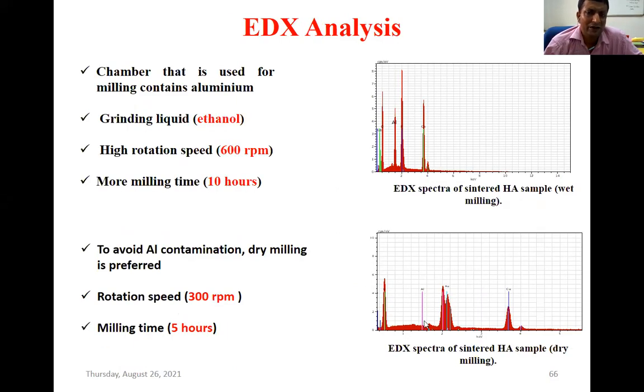Now coming to the big issue related to high energy ball milling, and why it's not being used to a greater extent. The big issue is the chamber we are using. The balls are rotating at very high speed, and the time duration is also very long, normally 10 hours. So contamination is the big issue in high energy ball milling. We did EDX and obtained an unwanted aluminum peak from the jar we were using. This is a big issue in the case of energy ball milling.